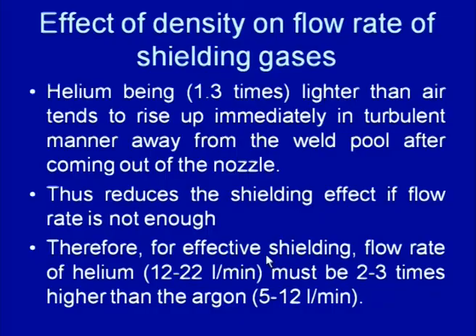Under conditions where helium is trying to move up as soon as it comes out of the nozzle, to achieve the desired shielding effect the flow rate must be high enough. For effective shielding, the flow rate of helium must be about 2 to 3 times greater than argon, because argon is much heavier than helium.